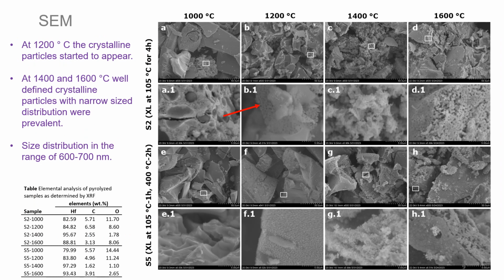Now, to investigate the morphology and particle dimensions of the hafnium carbide ceramics, which were pyrolyzed at different temperatures, SEM analysis was performed. At a lower temperature of 1000 degrees centigrade, both these samples showed agglomerated lumps in the powders. These agglomerated lumps supposedly consisted of hafnia and amorphous carbon, which reacted intensively to form hafnium carbide at higher temperatures.